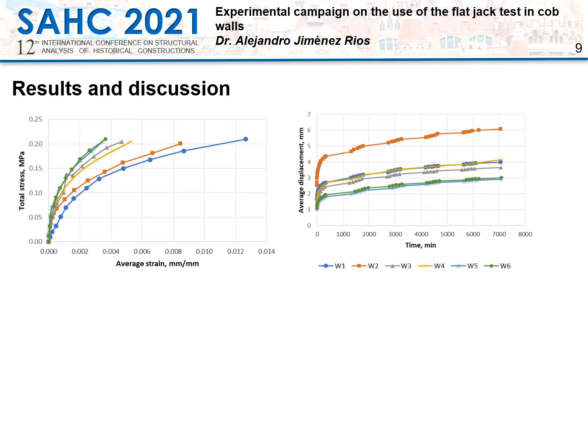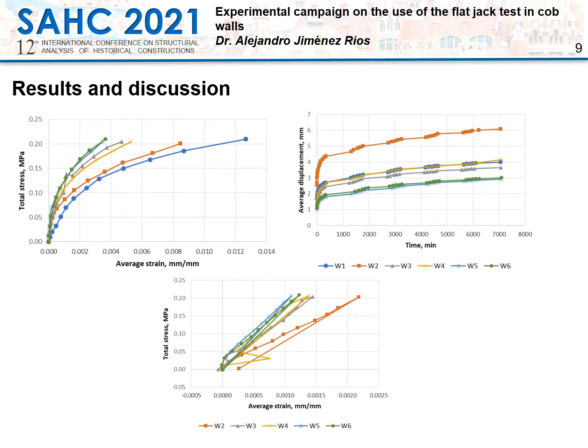As can be seen in this second figure, which represents the average displacement measured with the LVDTs under a constant load over time, the increase in average displacement between the fifth and the sixth state of consolidation, roughly between 6,000 and 7,000 minutes, for all wallets was practically null in comparison with the average displacement recorded during the first hours of the consolidation process, from minute 0 up to roughly 300 minutes, when displacement increments of up to 80% were observed. The last figure in this slide presents the linear behavior obtained after a second consolidation cycle. The mean Young's modulus value obtained was 143.3 megapascals, with a standard deviation of 32.6 megapascals.